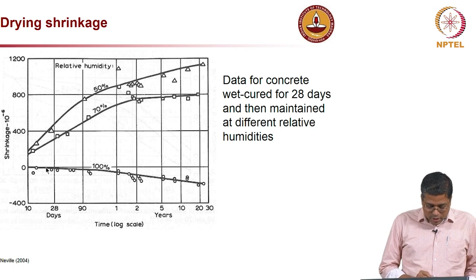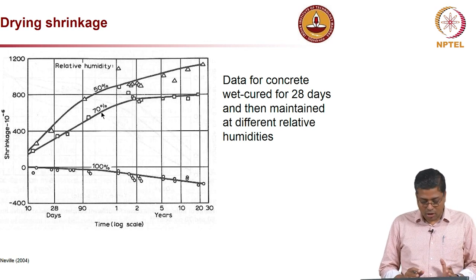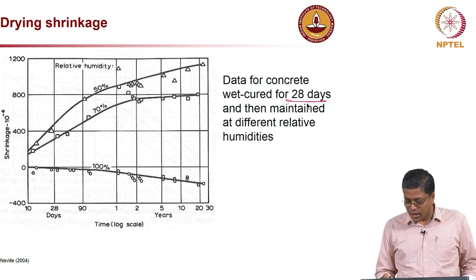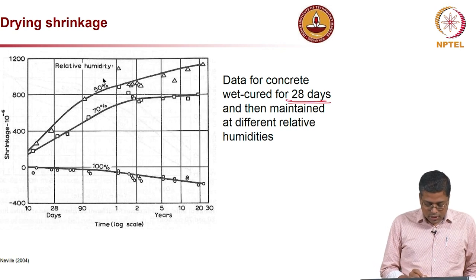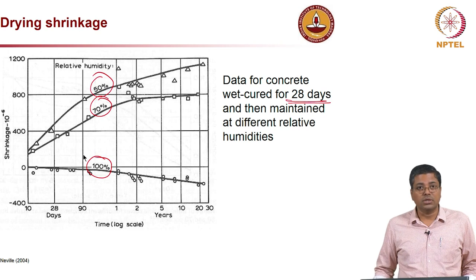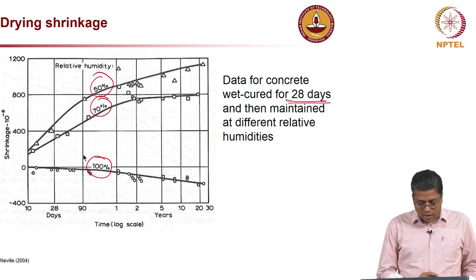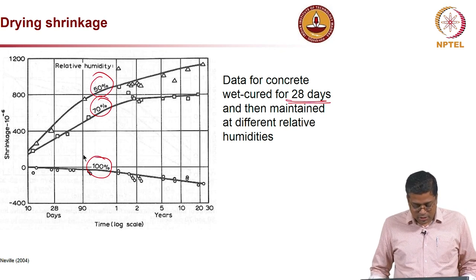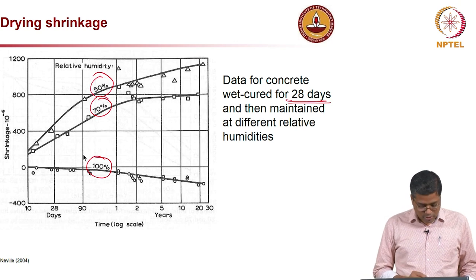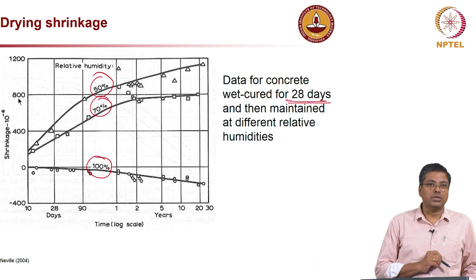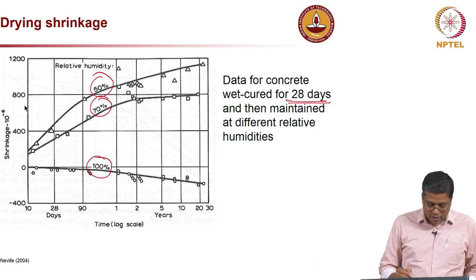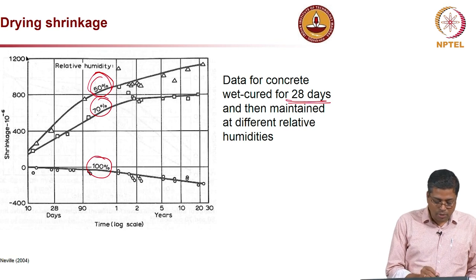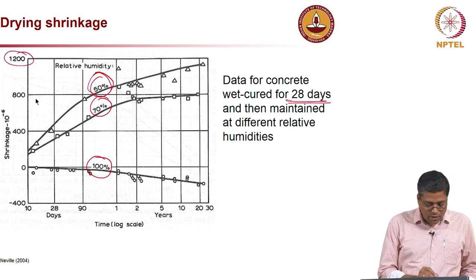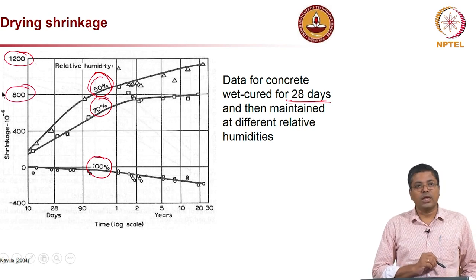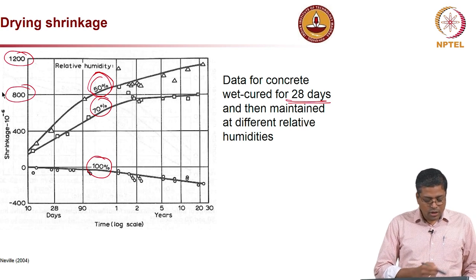Now, this graph shows drying shrinkage where all three concretes were cured for 28 days, moist cured or wet cured, and you see here this is 50%, 70% and 100%. After 28 days of wet curing, when the concrete was exposed to these three different humidity conditions, we could see very clearly that the amount of drying shrinkage is significantly high in the most dry environment in this case, which is 50% humidity, about 1200 microstrain. When the humidity was about 70%, the strain is only about 800, that is about 30% reduction.